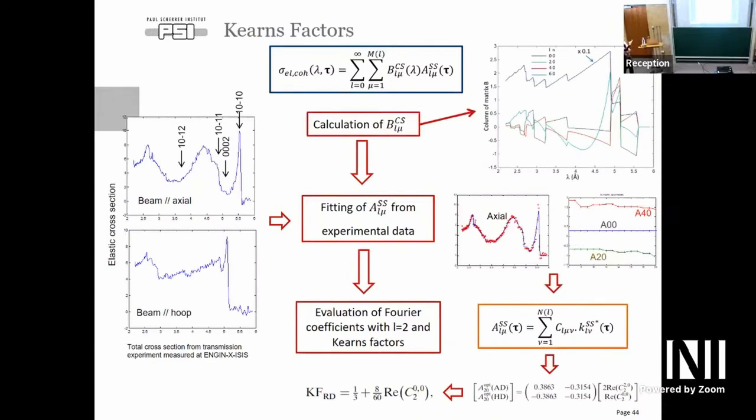Yep. In particular, in this case, I was working for the National Atomic Energy Commission, and this is a nuclear material. And in particular, the amount of crystal that you have with the C-axis along different orientations will link to how the hydrogen will interact with your sample. And that's a huge problem in nuclear material because it breaks, for example. So the whole problem here was trying to analyze the Kearns factor, because this will give us the information of how the hexagonals are aligned.